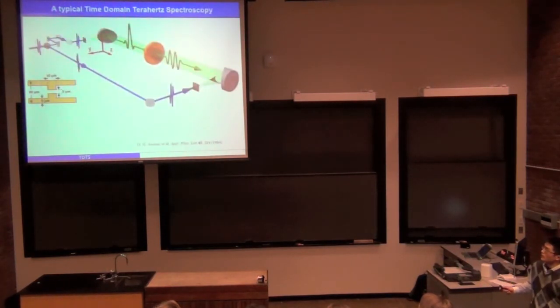And here I show you a typical time domain Terahertz spectroscopy setup. Here we would have a femtosecond laser pulse coming that gets split at the beam splitter. One pulse gets directed here, another pulse goes through a delay stage and hits what we call the emitter. This is a zoom-in view of the emitter. It's just a dipole switch. Here we have gold, usually deposited on low temperature gallium arsenide. When the femtosecond laser pulse hits it, it creates photocurrent. And then the oscillating photocurrent would act as a dipole. As a result, it emits a Terahertz pulse, which travels down this path.